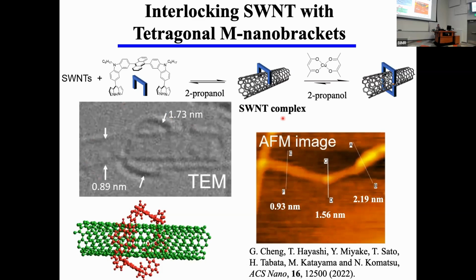And in this case, we probably assume that this structure is not interlocking, but coordination bonding forming the complex. And the size is 1.56 nanometer. Here, when it's fully interlocked, the height becomes higher than 2 nanometer. Anyway, we think we can see these three kinds of complex or uncomplexed structures by AFM. And of course, from the interlocking structure, we expect much better